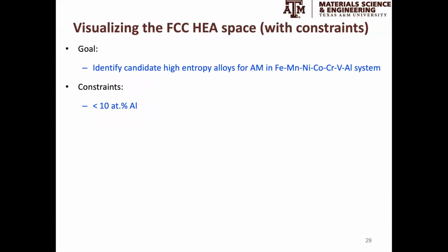Here I'll talk about two specific cases for search of the high entropy alloy space. In the first, we look at face-centered high entropy alloys, specifically the Cantor system plus vanadium and aluminum. We set some constraints: we don't want systems with more than 10% aluminum, and we want alloys that are single phase FCC at 800 Celsius.